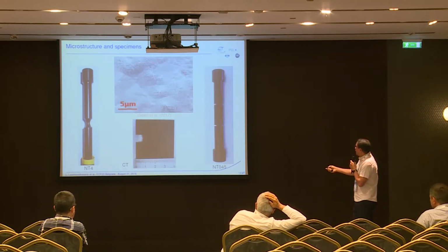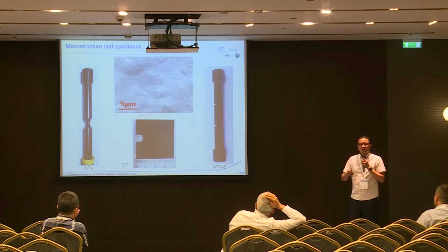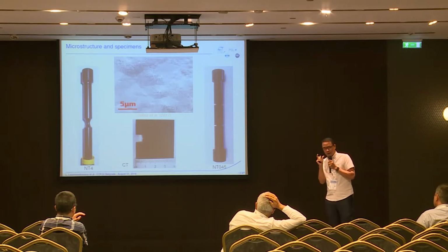And then we have the nucleation. We have observed with the nanotomographic data the nucleation of voids inside the spherulite. The size of the spherulite is about 5 micrometers, so we have this characteristic length for the material.